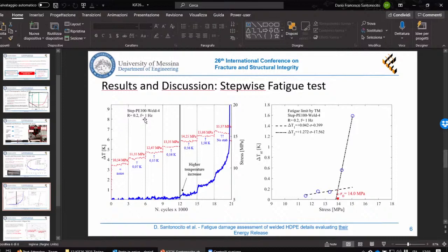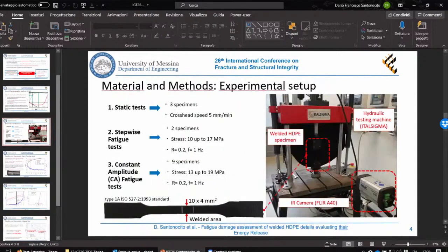Okay, are there any issues in preparing the setup of the test? I wonder if there are any issues in calibrating the thermal camera. No, because we adopt the relative temperature increment relative to the first thermogram of our investigation. It is important to have a specimen with a high emissivity surface. As you can see, this specimen is black, but in general we have to paint the surface with black paint in order to increase the emissivity of the material. But in general, it is really easy to perform this kind of test.